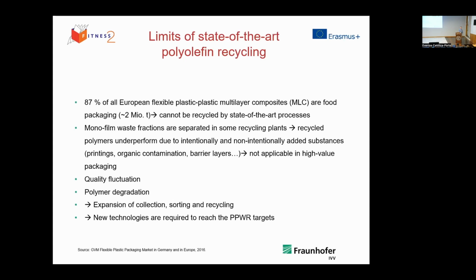And monofilm waste fractions are separate in some recycling plants, but the recycled polymers underperform due to intentionally or non-intentionally added substances such as printings, organic contaminations from food, for example, or barrier layers. So it's not very likely that they can be applied to high-value packaging. Furthermore, you have a quality fluctuation because not every waste batch is the same. You also have a polymeric degradation due to the high thermal stress during the extrusion.